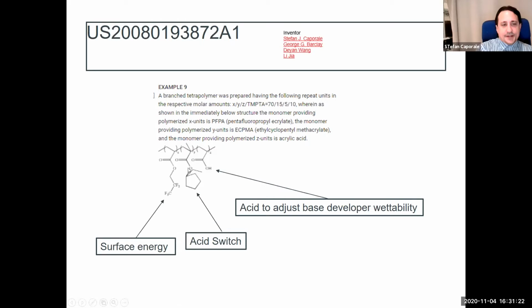You have a switchable material in here. So again, this is another example of a leaving group. This allows in the exposed region you to form a lot more acid, which allows the film to be wetted. One of the first problems we ran into with this is that it was great. We can make a surface, we control the contact angle of water, but our developer is in water, and we need to have that contact the material and develop.